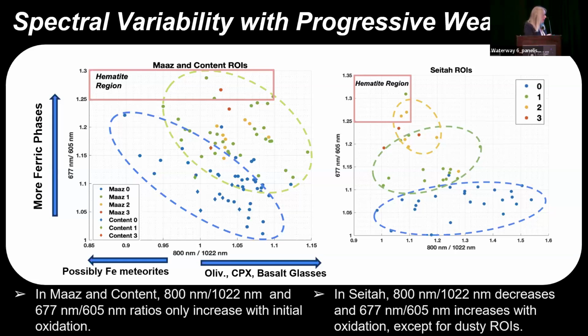So we found that we were able to produce 2 distinct groupings for Maaz and Content, and that the values associated with this oxidation progression have the effect, going from the least weathered to lightly weathered ROIs, of increasing both your 677 over 605 ratio and the near-infrared ratio. However, there's no additional change after that initial stage of weathering that makes any kind of predictable change in this parameter space. But for Seitah, we do see predictable changes in this parameter space with increased oxidation. So going from the least weathered to slightly more weathered and then up to moderately weathered, we can produce 3 distinct groupings. So the spectral changes are more predictable for the dunites than they are for the more intermediate to mafic compositions.